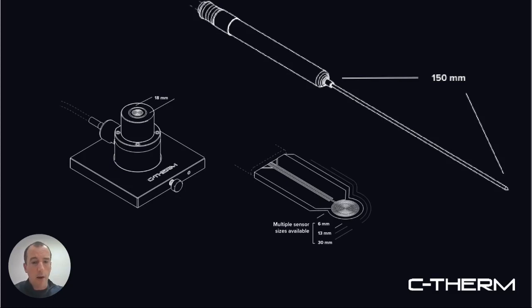So the needle requires the largest volume of material. With the Flex, you have to have two samples and you sandwich that sensor in between the two samples. And then the MTPS has a very small active sample footprint, so you can get away with testing some of the smallest sample volumes. And you only need one interface with the sample, which gives you some advantages in testing irregular shapes and maybe some samples that are difficult to scale up, produce, or machine.